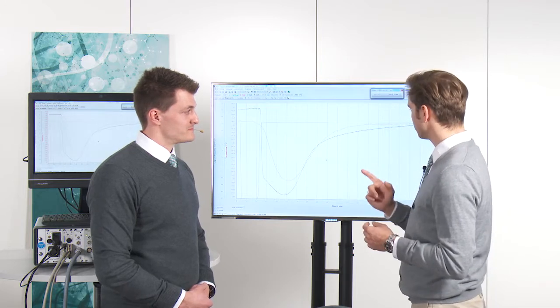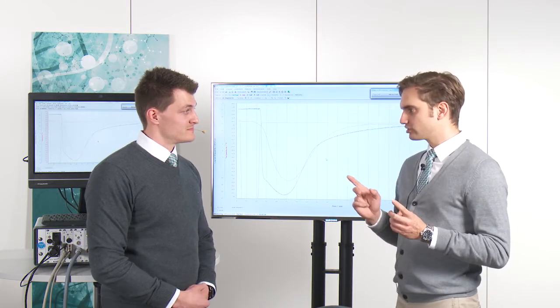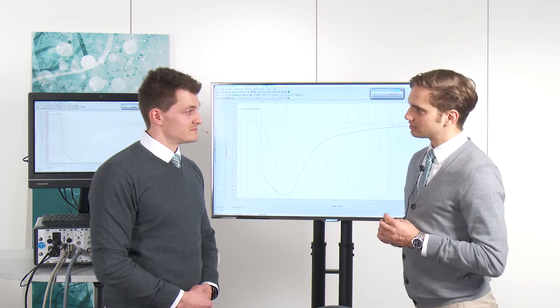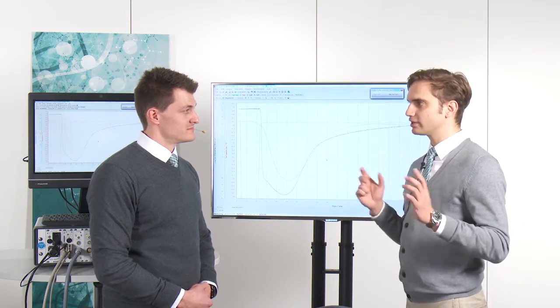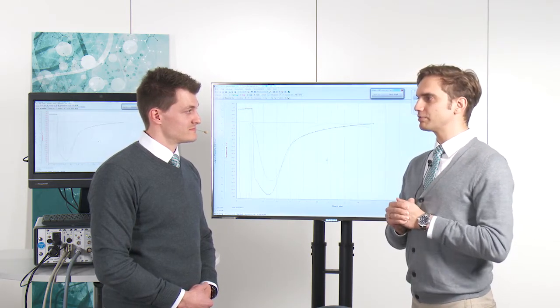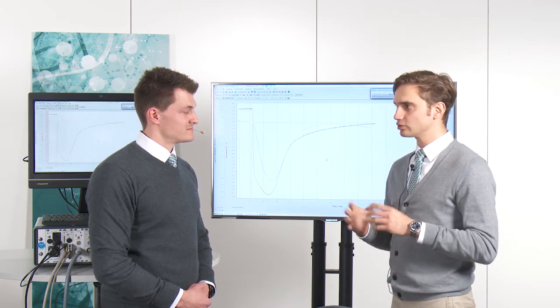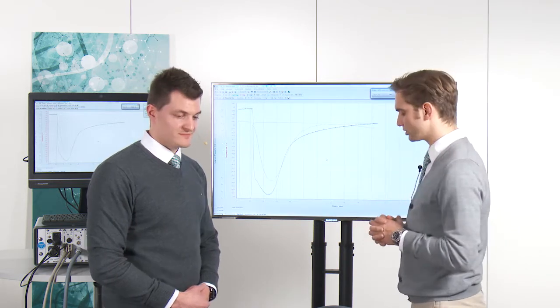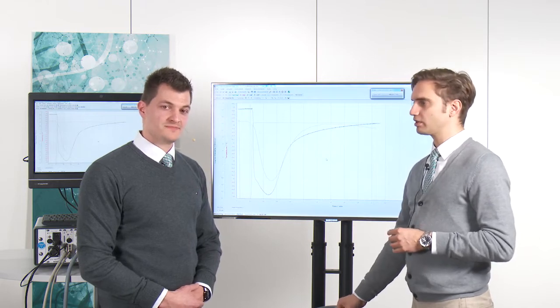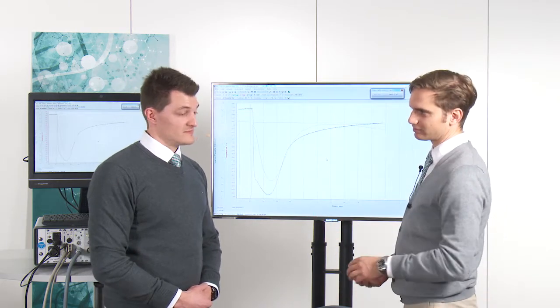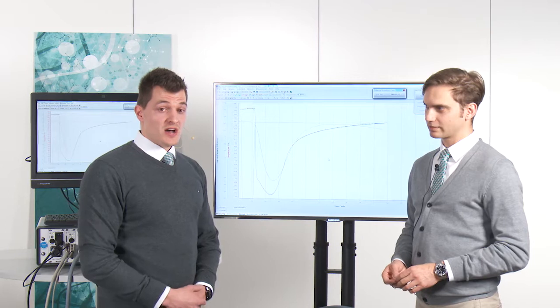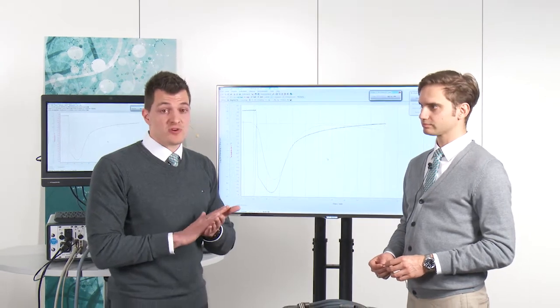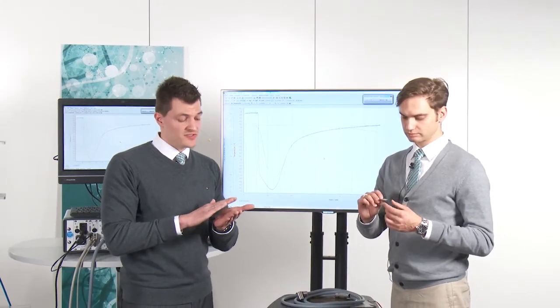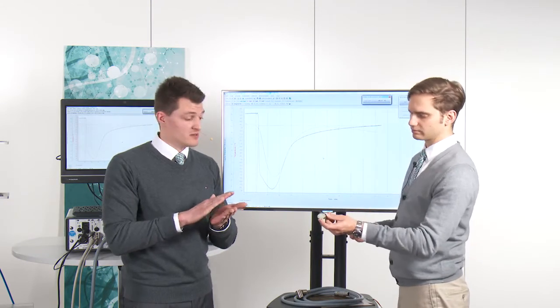Second question, relating to carbon fibers. This is a conductive material, and actually it's not easily possible to measure a dielectric signal to follow the curing of carbon fiber parts. How did you do that? Yes, for sure. You're totally right. We have to put in a separating material. So we used glass fiber woven fabric between the dielectric.